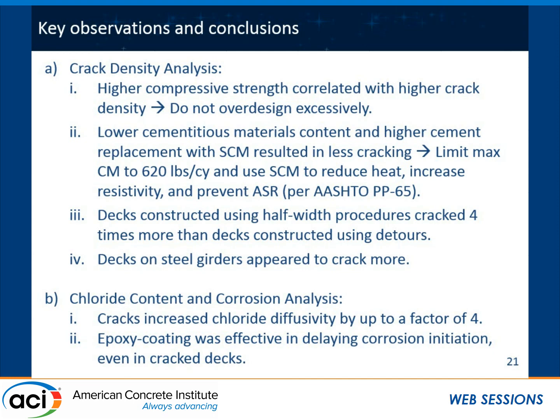You'll have a lot of traffic control issues to deal with, and there are a lot of cracks that you have to map and so on. So we tried to streamline the process and minimize the time that, for example, a lane was closed to traffic. So kind of a long answer of saying we didn't measure the crack widths across every crack. We measured selectively.